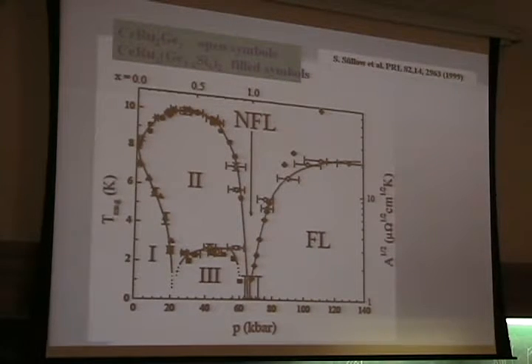And in this work of Süllow, he did high pressure studies in this system, and also compared with doping with germanium and silicon. In both cases, the ferromagnetic transition seems to give way after some pressure to another kind of ordering that can be anti-ferromagnetic. That's not very clear, but the ordering changed. And as in my system, when I doped it with iron, there is also an indication that the ferromagnetic order changed to anti-ferromagnetic with pressure and with doping.